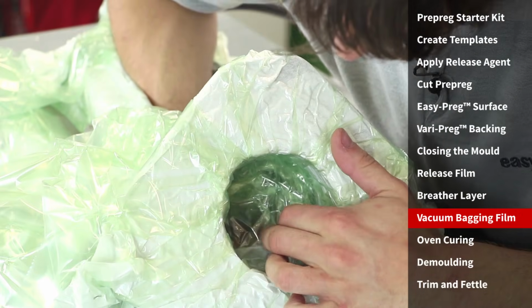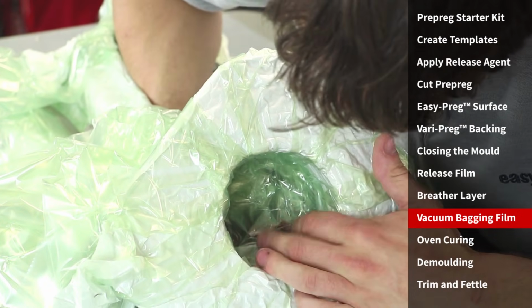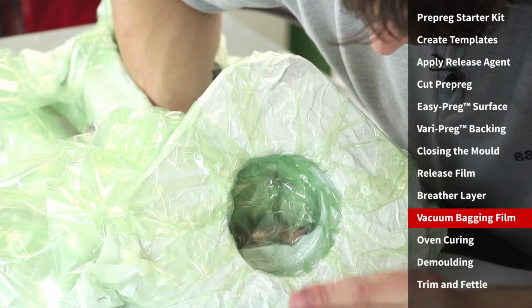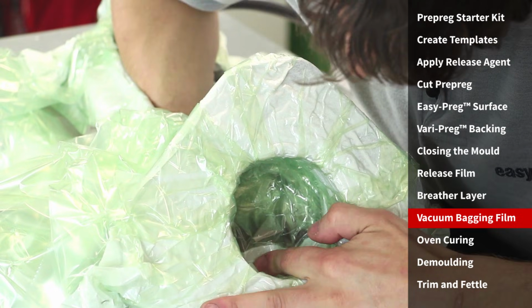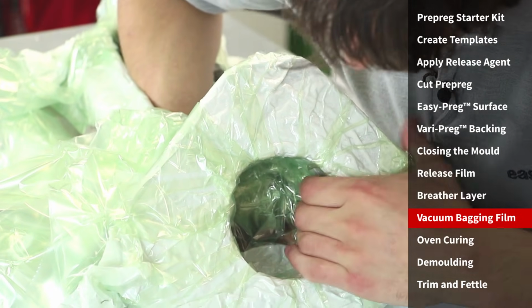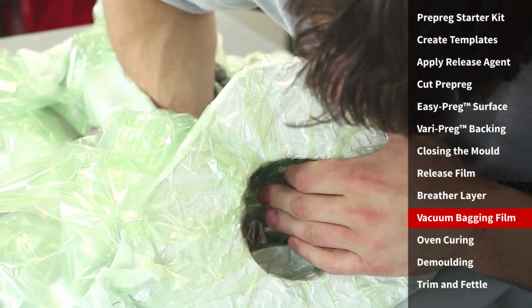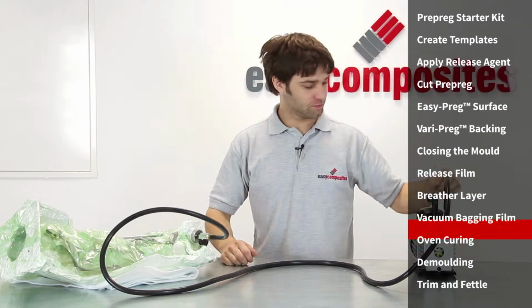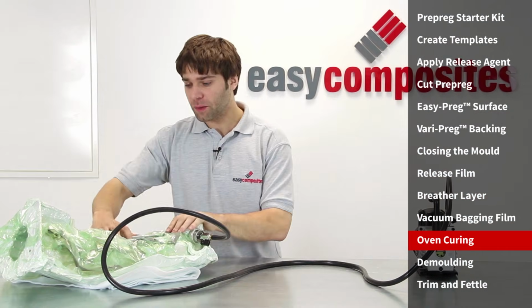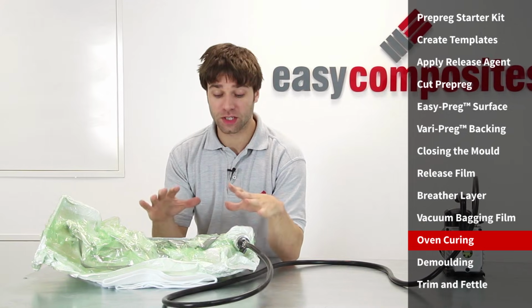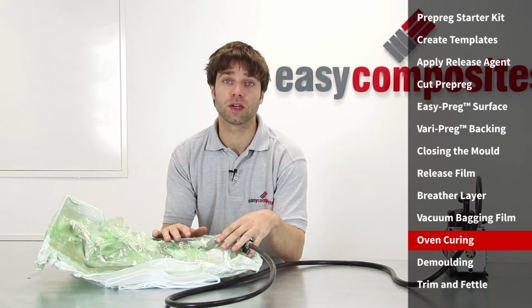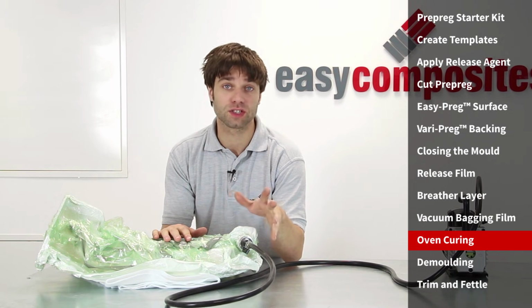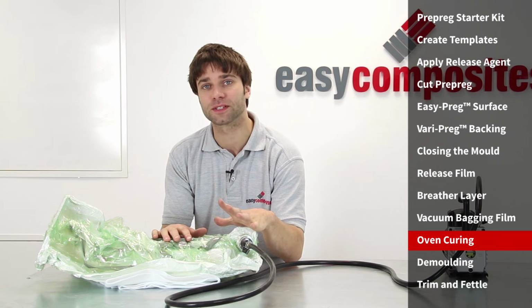You can see here where the vacuum bag that's been pushed into the neck from the inside meets the bag that has been pushed in from the outside. We need to make sure that there's no bridging around the outside of this area too. With the bag fully pulled down, all that's left to do now is cure this part. To do that, we're going to be curing this at 80 degrees C, which is 176 Fahrenheit, for 8 hours.